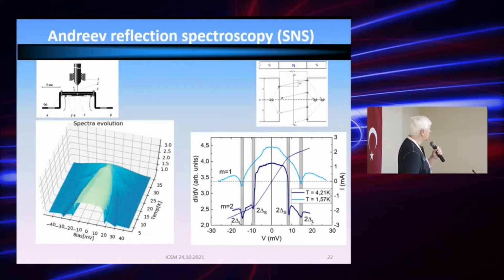At the moment, there is nothing additional to say about the superconducting state, and we used another instrument, which is the break junction technique. Yesterday we attended 2 talks on this technique, so I will not explain what is going on. We cleaved the sample again in the cryogenic environment, and we tuned the cleft in such a way that we observe the Andreev type IV curve, where the zero bias conductance is twice larger than in the normal part. In this mode, we observe several resonances which can be identified with the 2 gaps. And this 3D picture shows how these superconducting gaps evolve as a function of temperature. They clearly close at the same temperature.